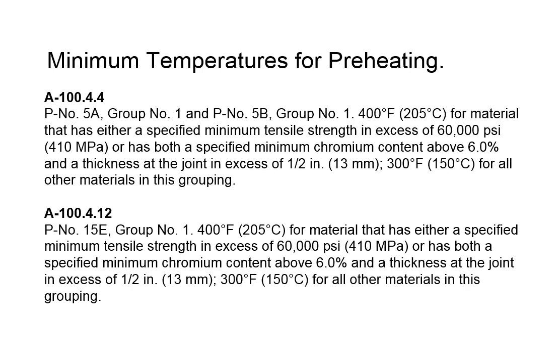And they also throw in there in the 5A and 5B, you need to look at the materials and what's the chromium content. So there's some things you really need to look at. So for P15E, I worked for a company that used to do some P15E material. And this is 400 degrees F before, and a tensile strength in excess of 60,000. Most of that stuff does. And then you have to look at the chromium content. If it's above 6 and a thickness of the joint in excess of half an inch, you're either going to 400, and if you aren't going to 400, you're going to 300.